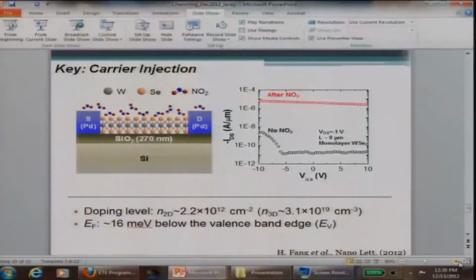So we started using surface charge transfer. This is something that we learned by working with carbon nanotubes and graphene. In this case, we exposed the semiconductor to NO2 gas. NO2 molecules are known to be highly oxidizing. They withdraw electrons out of the semiconductor surface. By doing that, they create holes in the semiconductor.